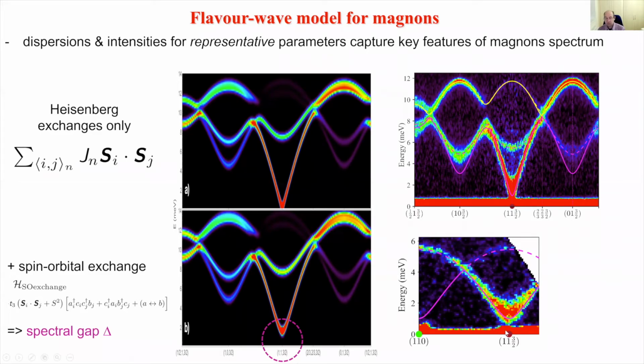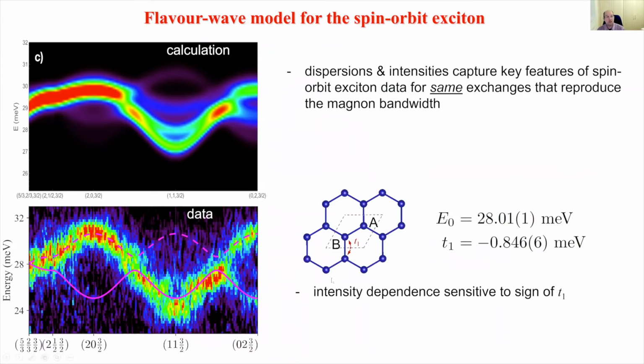as seen experimentally. And then this flavor wave picture provides a mechanism not only to explain the magnons, but also to explain the high energy excitons. And here is the calculation, and it resembles the data very closely. And this is a non-trivial agreement because we've used essentially the same exchange interactions via projection to describe both the exciton dispersion and the magnon dispersion. So fundamentally, it's the same exchange that produces hopping, but for different types of quasiparticles.